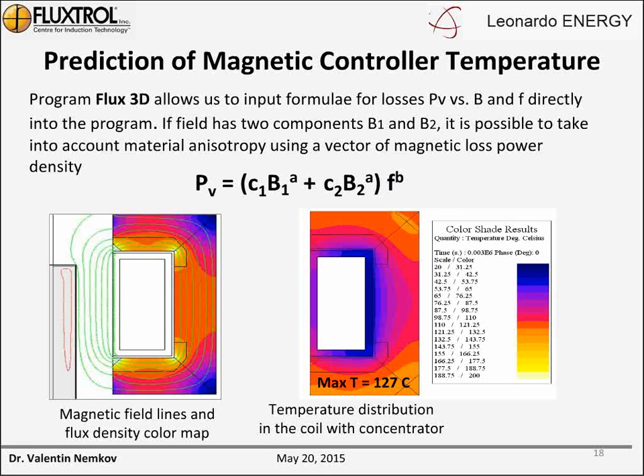How to predict that? How to receive these results? If we use a program Flux 3D for simulation, it allows us to input a formula for losses PV versus flux density B and frequency directly into the program. If the field has two components, B1 and B2, it's possible to take into account material anisotropy using a vector of magnetic loss power density. I actually forgot to mention that all pressed materials have certain anisotropy.